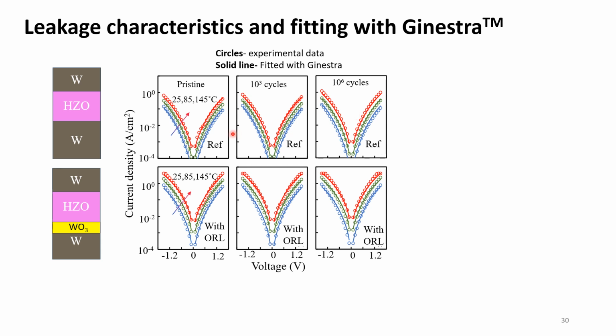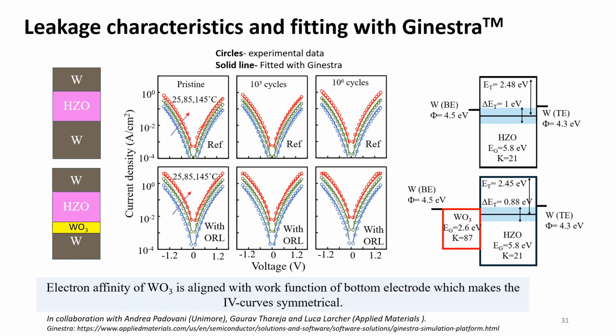Next, we used Ginestra to fit this leakage data. Ginestra is a commercial device simulation software from Applied Materials which can describe carrier defect interactions in the devices. So we used that software to fit the leakage data for both the devices. You can see here that the circles are coming from the experimental data and the solid lines are the fitted data using Ginestra. After fitting this data, we could find the band diagram for both the devices.